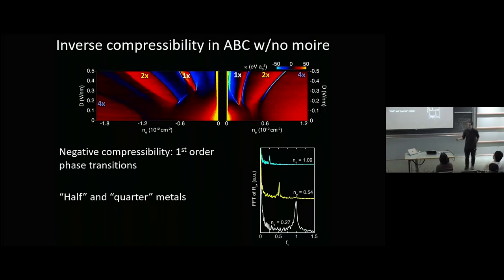Now you can crank up the electric field, and what you see is actually that half metal state is that tiny little feature. But as you increase the electric field, it's joined by all of these different very strong features. What I'm plotting here is actually electronic compressibility, or rather inverse compressibility. So where you see these bright blue features, that's where the compressibility is negative. And each one of these, these strong ones, are first order phase transitions between different types of ferromagnetic states that polarize into one or more of these spin and valley flavors, and additional broken symmetries as well. So just to give you an example, if I take this Fourier transform out here at high density, even at high electric field, I find that I have my peak at 1/4, and that's precisely my symmetric state.